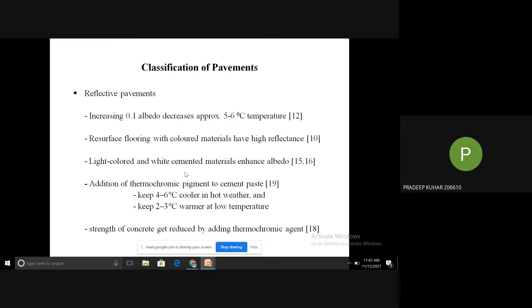For this purpose, we can increase the reflectance of the surface by using light colored materials, and in the same direction, in 2009, it was stated that it is desirable if a pavement surface has high reflectance in summertime but low reflectance in winter. This can be possible by utilizing suitable thermochromic pigments with adequate doses. These pigments can lower the temperature by 4 to 6 degrees Celsius in summer, and they can enhance the temperature by 2 to 3 degrees Celsius in winter. In the same direction, in 2020, a study was conducted, and it was identified that the strength of concrete gets reduced by adding these thermochromic pigments into the pavements.